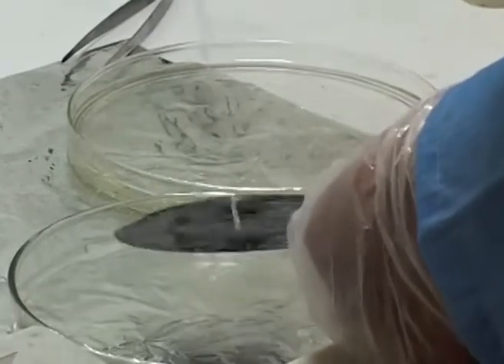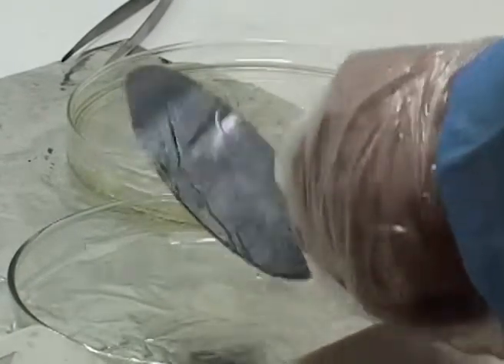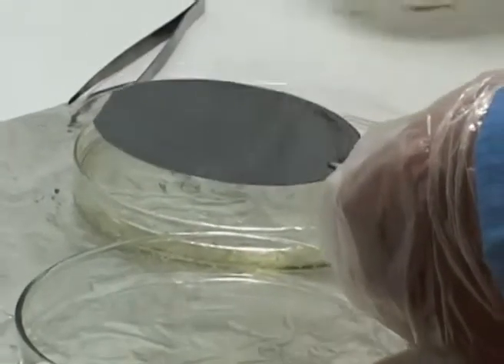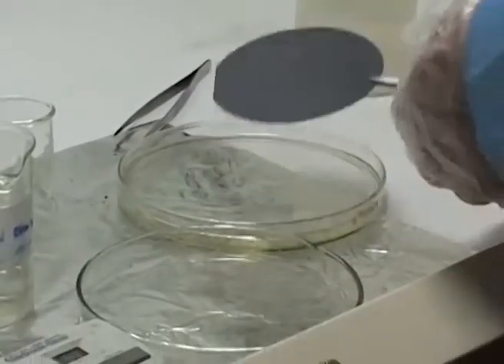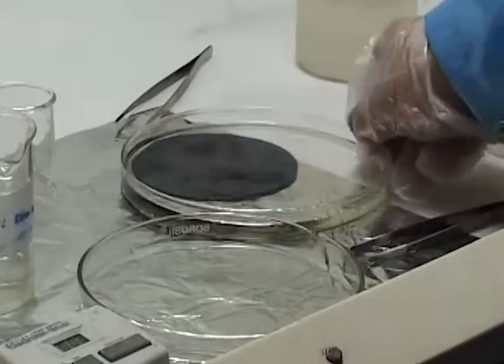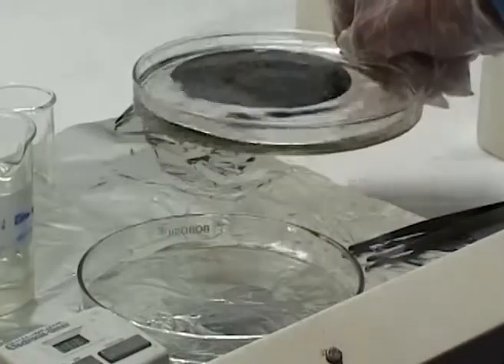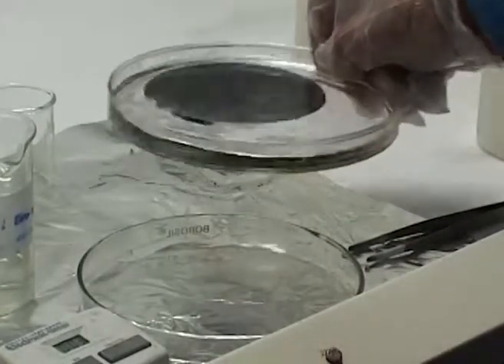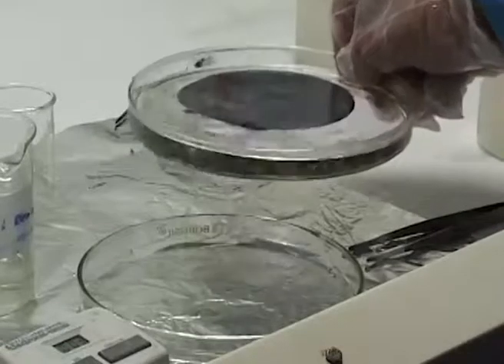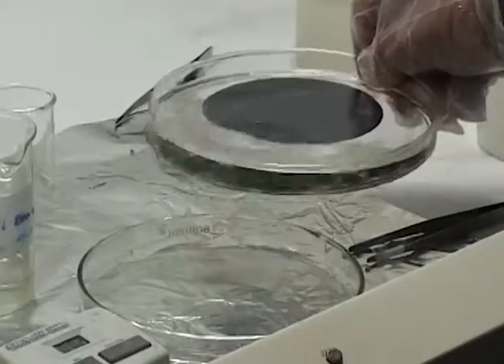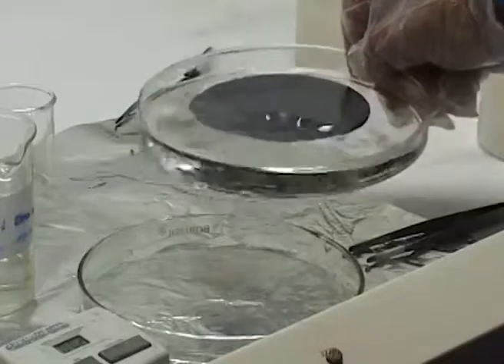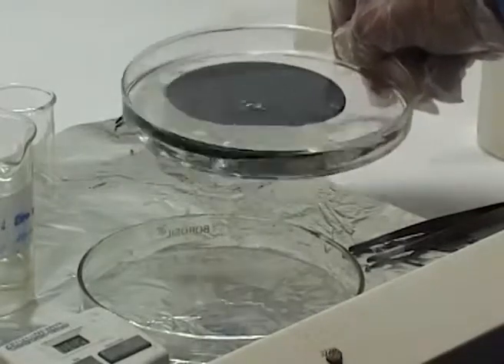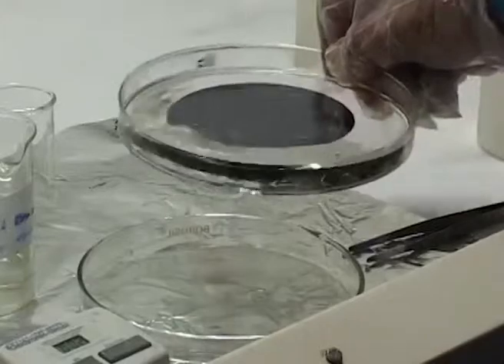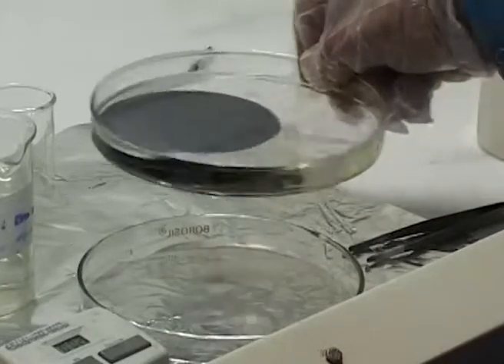I see that there is some clouding action which has happened, which means that undeveloped resist is still present. I put it back into the solution and again try to just give it a few turns and see. So this process keeps on going for the stipulated time, and at the end of the process you'll have really sharp, distinguished features which come out.